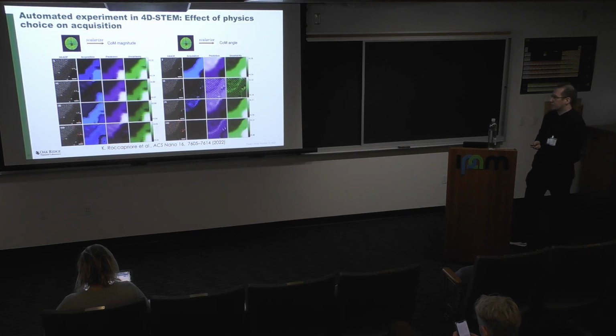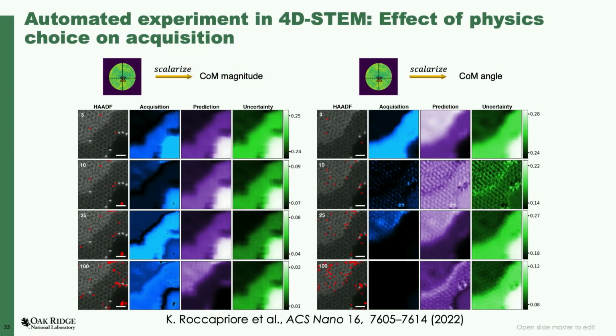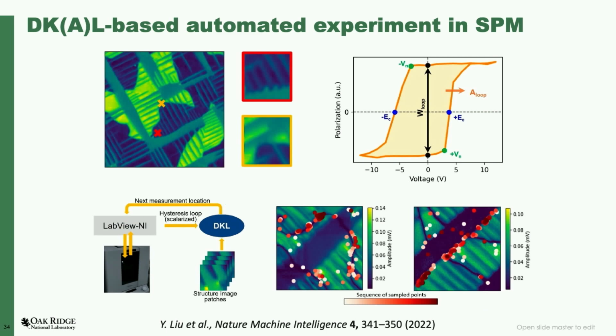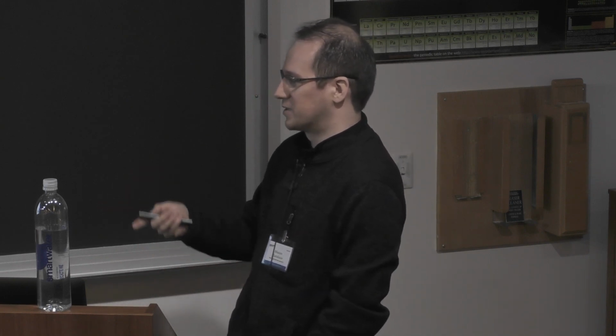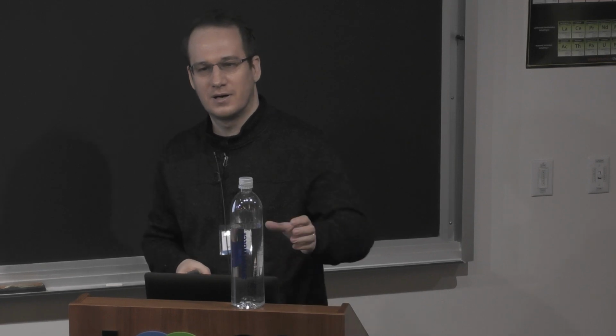Yeah, we can extend it to other materials and measurements. In this case, we were looking at the correlation between the structural data and the local electric and magnetic fields that could be measured through the so-called 4D-STEM measurements. And we found some very interesting correlations, which we are still trying to understand, but the point is that it works. And again, it's not limited just to atomically resolved data or electron microscopy. We transferred this technique to scanning probe microscopy, where we were able to identify different types of topological defects where a particular ferroelectric switching behavior was maximized. So that was pretty cool. The interesting thing is that it took us so long to publish our first proof of concept paper that this paper actually came first, even though it was experiment number 4. So it was funny. Okay, so finally, I don't know, do you have any questions?